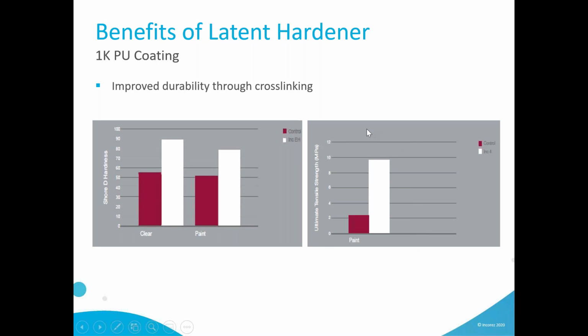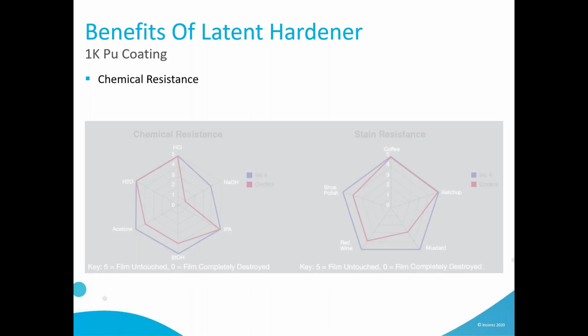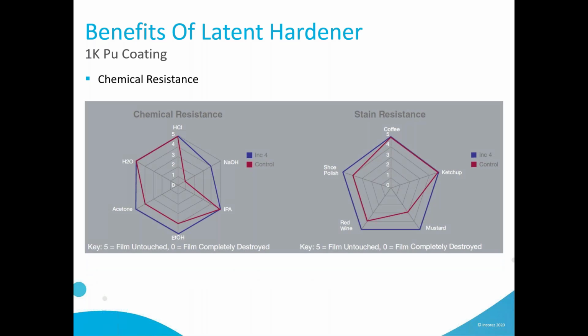While typical PU1K systems have a tensile strength of 2 or 3 megapascal, the system with Incozol 4 here can nearly achieve 10 megapascal. The fact that your system has better cross-linking will also enable you to have better chemical and stain resistance, as shown on those graphs, which make them more suitable for heavy-duty flooring.